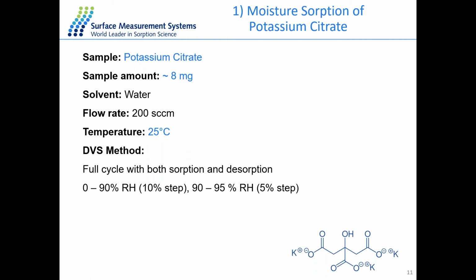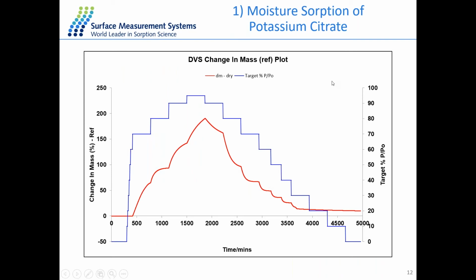So here we have the mass plot of the experiment. And as you can see, the sample is pretty stable below 60% RH. There is almost no uptake at all. And from 60 to 70% RH, it begins to pick up lots of water. And at 95% RH here, the mass change could reach almost 200%, and it's still not quite at equilibrium yet, which is just basically the condensation of the water droplet on the sample pan.